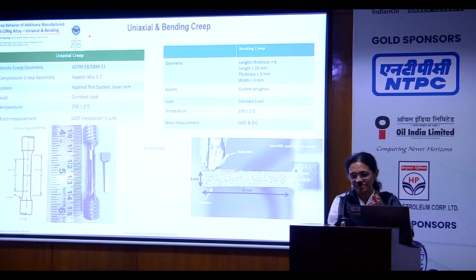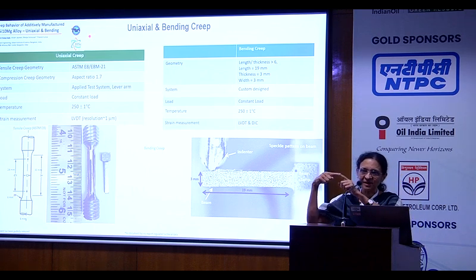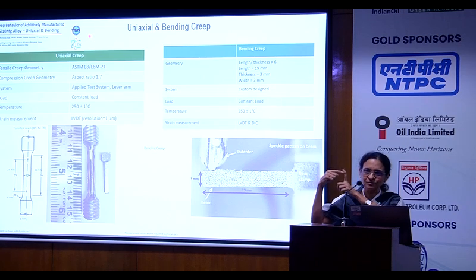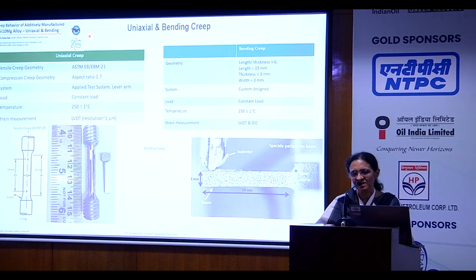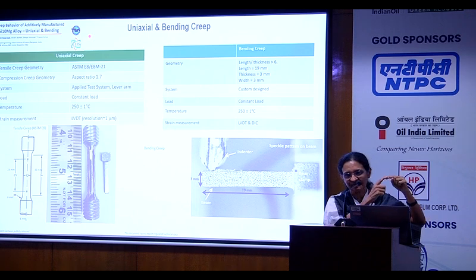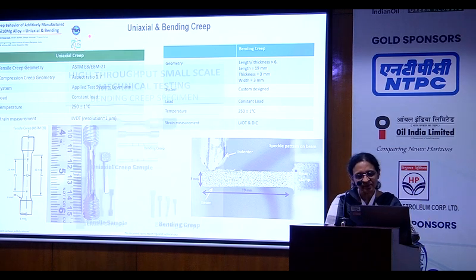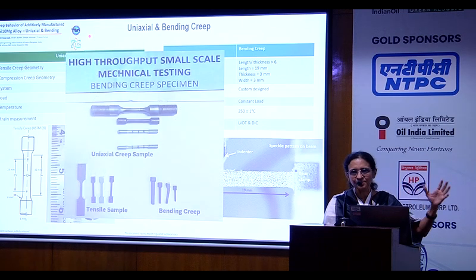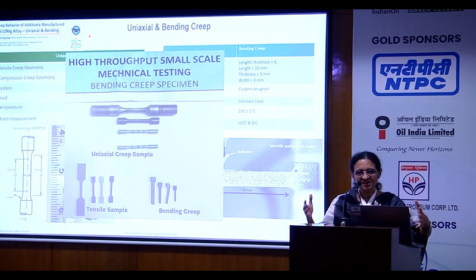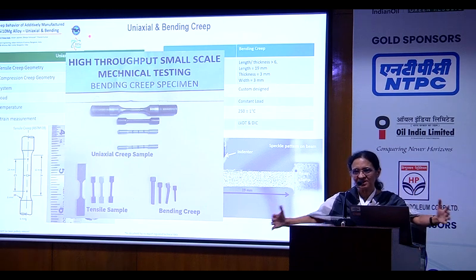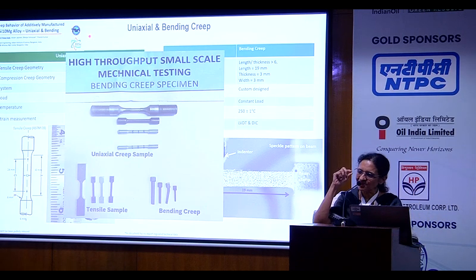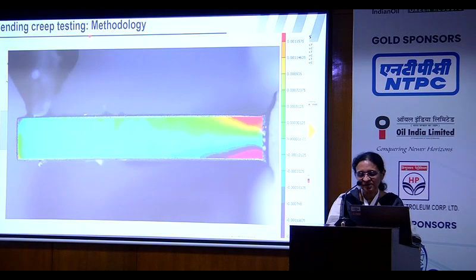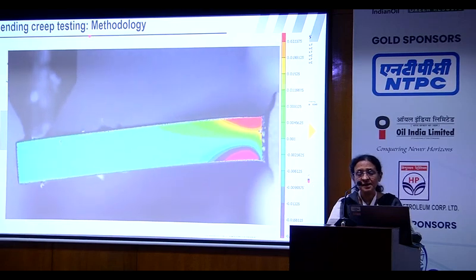So it's basically a high throughput testing, and the technology involves a completely different paradigm shift to uniaxial tension or compression, and it's via a bending, a cantilever bending. We're all used to 3-point bending, 4-point bending in college, but this is single cantilever bending load. So I'll share a couple of videos. This is just to show in our lab that we have test specimens as big as this. We get large test specimens also, but we are talking of very tiny specimens with equivalence in mechanical properties.